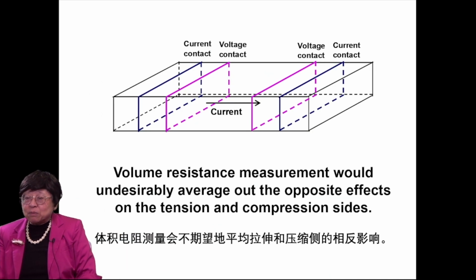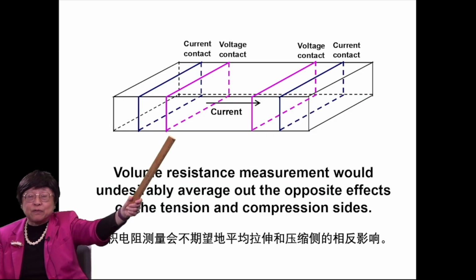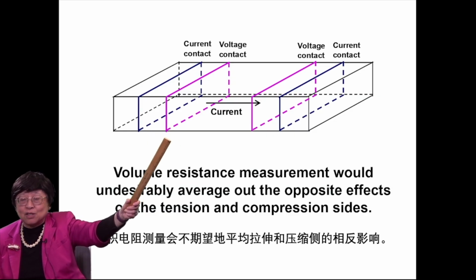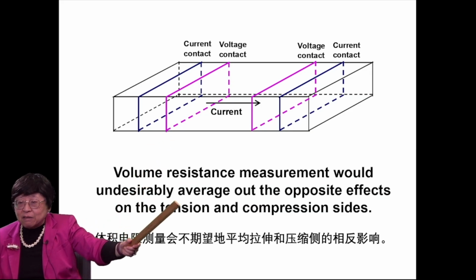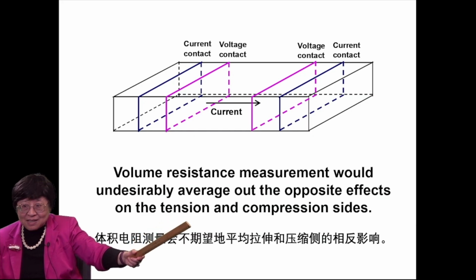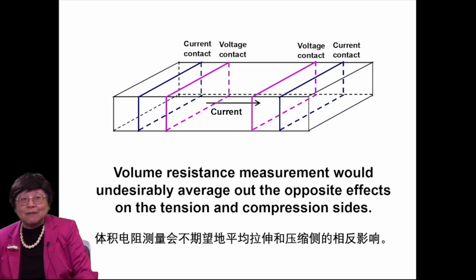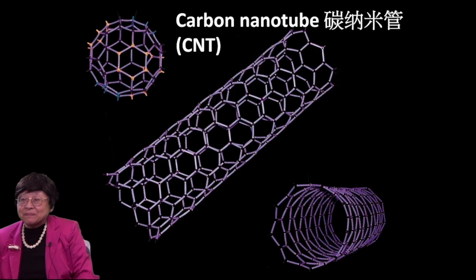The volume resistance measurement, if you use this instead of surface resistance measurement, you measure the volume resistance during flexure, like you use four-point probe contacts as opposed to surface electrical contacts. The volume resistance would undesirably average out the opposite effects on the tension and compression sides. So that would not give you much sensitivity in monitoring the flexure. However, quite a number of papers published use this method.